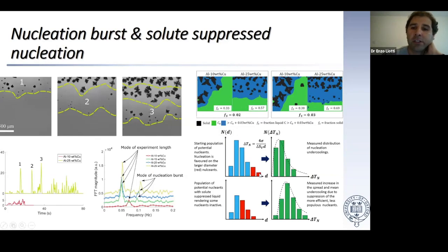The effect is that you suppress more of the easy nucleation, to achieve nucleation at higher undercooling. But the size distribution of the nuclei in the liquid is log normal. Because of this, if you kill the potent nucleants, which are not very numerous, you are able to activate more nuclei. That's the effect of solute. The cooling rate is not shown in this data, but it has an effect on the shape of the diffusion zone, and it can be explained with a similar argument. When you increase the cooling rate, you narrow the diffusion length and you increase this effect.